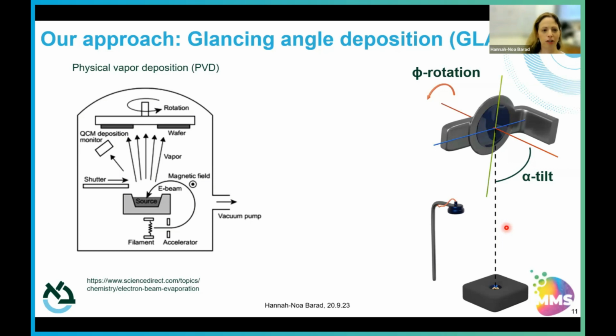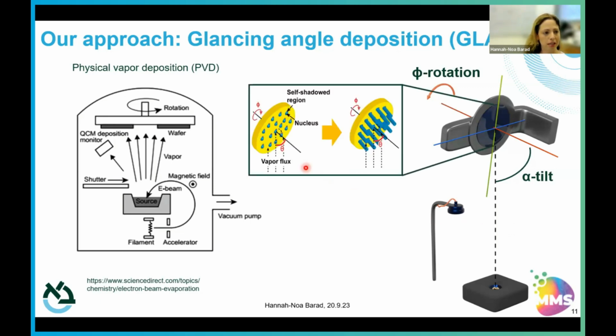So what happens when you tilt your sample to high angles? Well, you have some initial vapor flux gradient, vapor flux coming in onto your sample. And of course, samples are never straight. They always have some kind of tiny roughness to them. And that is where your initial seeding points form. And this happens within the first few nanoseconds of the deposition.